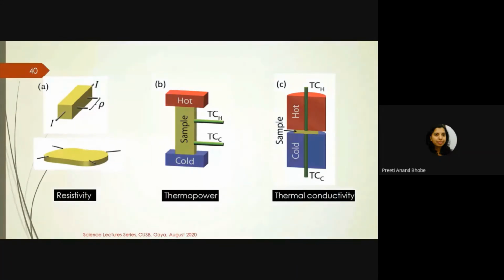And when you try to make a densely packed pellet, you find that the morphology-related features of that pellet are lost. You may still have rods, but all the rods are meshed up and held in a pellet, or the flower morphology is broken away, so morphology-wise you cannot make a distinction once you make a pellet to measure thermal conductivity or Seebeck coefficient. Resistivity still shows the effect of the morphology, but for a sample used for thermopower or thermal conductivity, with the change in morphology of the nano, you don't really get to see a change.